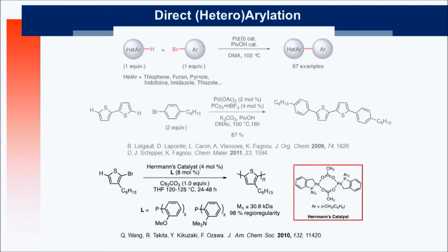Another work at the same time from Ozawa in Kyoto showed that it's possible to make this very important polymer, P3HT, from a direct arylation polymerization. The head-to-tail coupling is 98%. So it's a well-defined polymer from this direct arylation. So you have the coupling between the bromo here on the CH bond here.